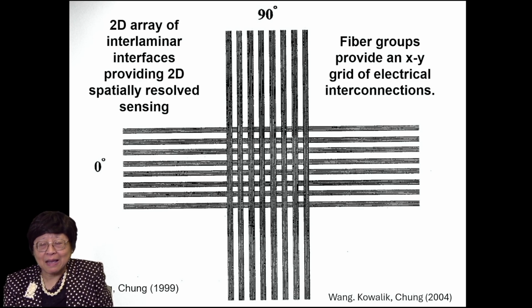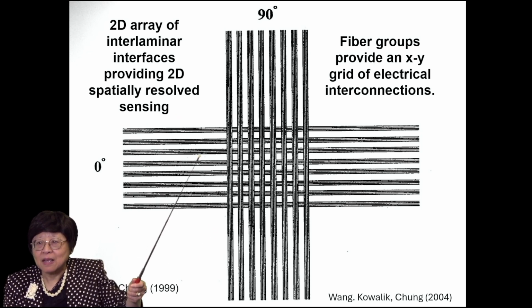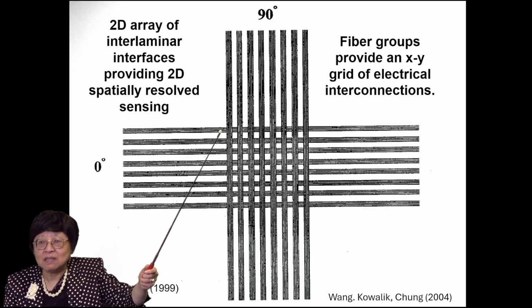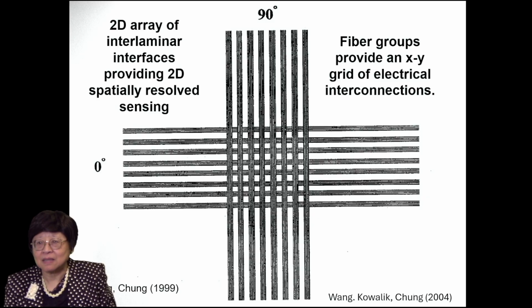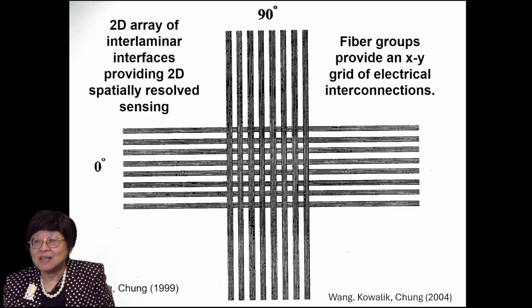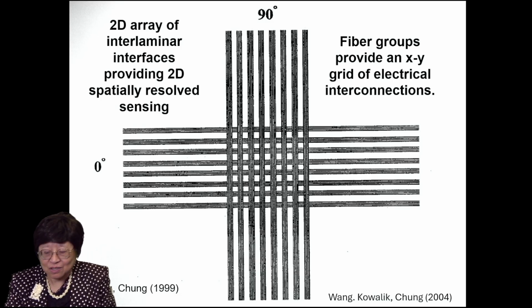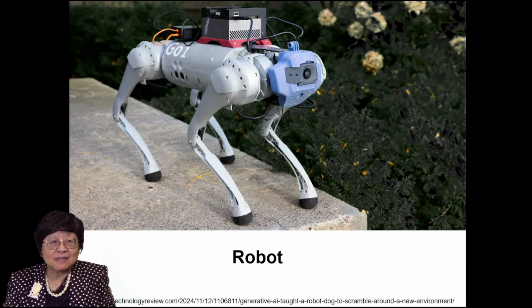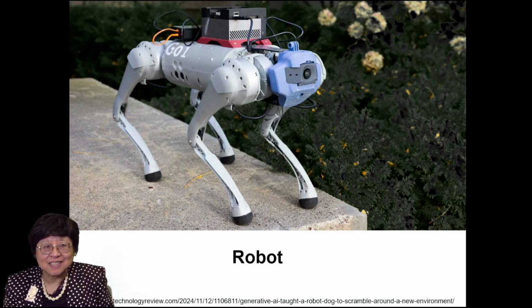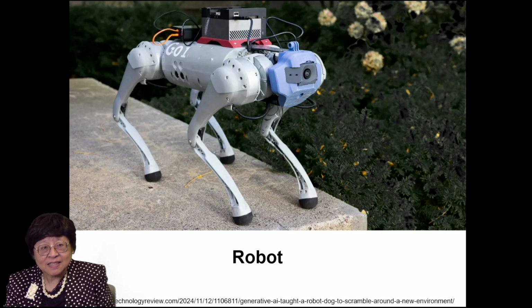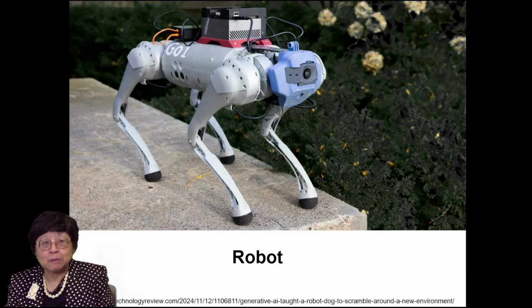Another nice thing about the interlaminar interface is that you can have an array of interfaces. Here you have fiber groups in X and Y, and you have a junction, and so you have an array of junctions, and that's an array of interfaces, meaning an array of sensors. And thus we can do 2D spatially resolved sensing. In addition, the fiber groups, in this case X and Y, provide a grid of electrical interconnections. Now, robots also are smart structures, and you need sensing, actuation. So a lot of the concepts that I talk about are applicable to robots.